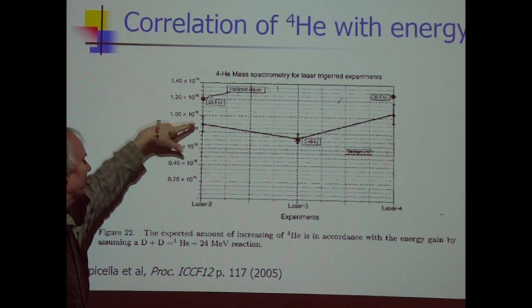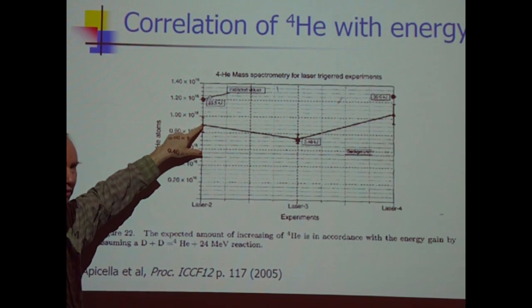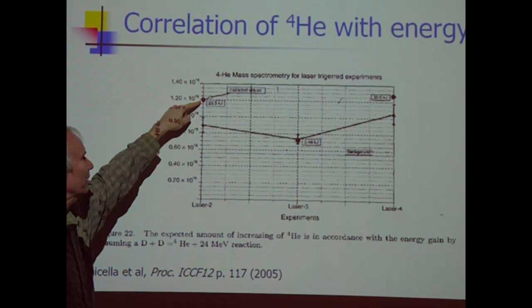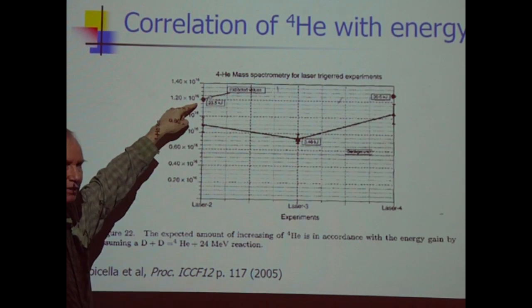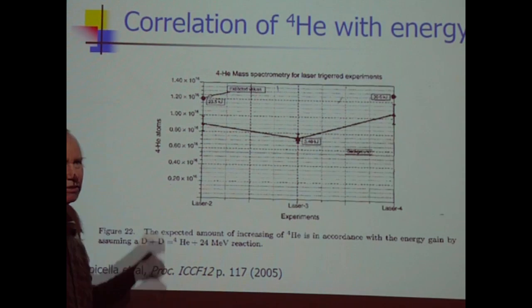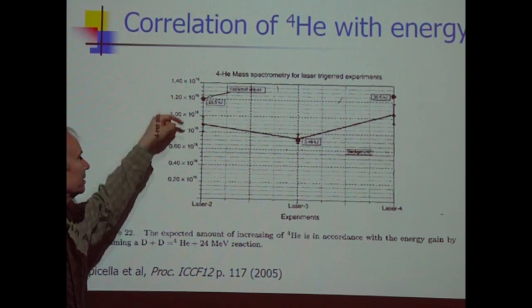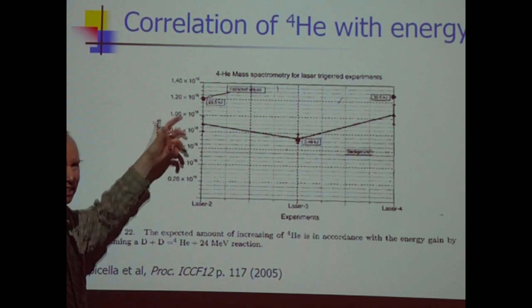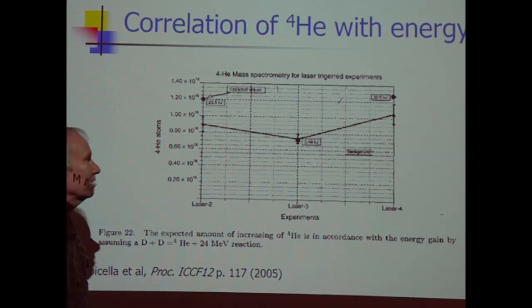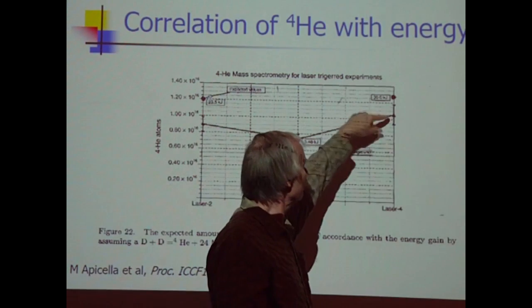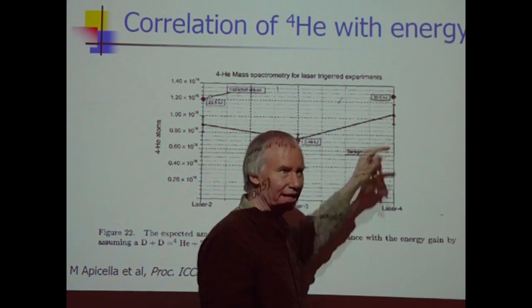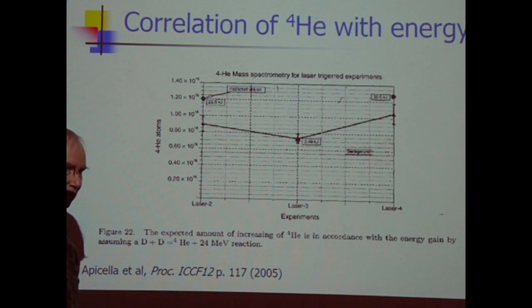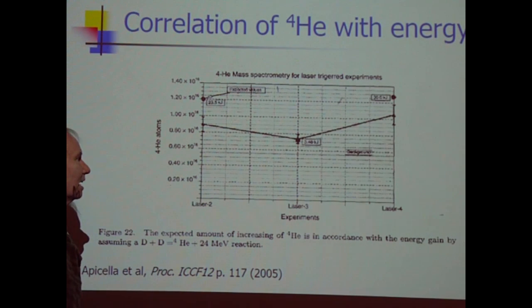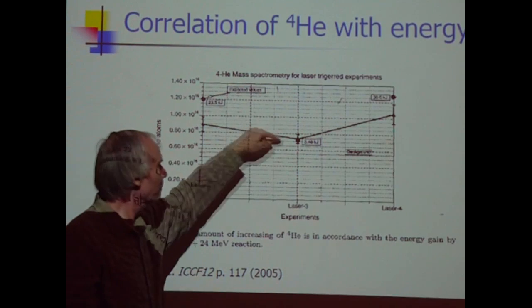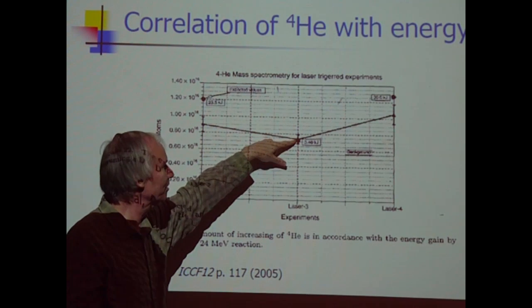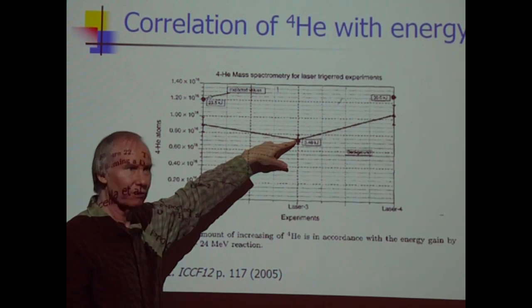This amount of excess heat was observed. This amount of helium-4 was observed. This is the amount of helium-4 that you would hope to observe based on the amount of energy that was produced. But in this experiment, there was no effort made to scrub out the retained helium-4. So between here and here, maybe you're getting 70% of the helium-4. Same thing over here. Amount of energy, helium-4, you're getting 70+% of the helium-4 that you would expect to observe based on the energy. Now here, you have a different experiment where energy was produced and helium-4 was observed.